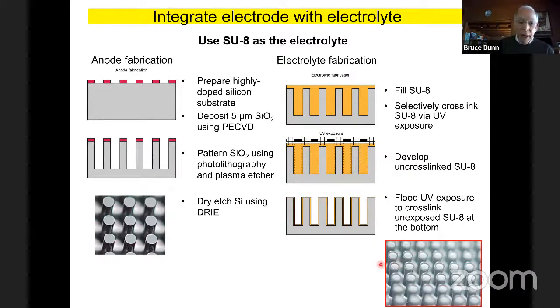In our case, the electrode was silicon. We're not going to fully lithiate the silicon because we don't need that much capacity. We're just going to partially lithiate, like 5 or 10%, which is plenty for the battery. So you don't have to worry about the silicon fragmenting. You make silicon arrays by standard DRIE processing.